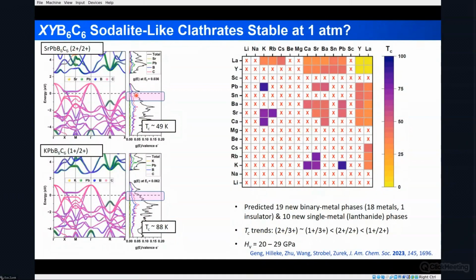Systems that have an average valence of 2+ are close to this peak. For example, this phase with a TC of about 50 Kelvin. And then systems with lower average valences would have a smaller density of states at the Fermi level. And this is the reason why their TCs are predicted to be lower.